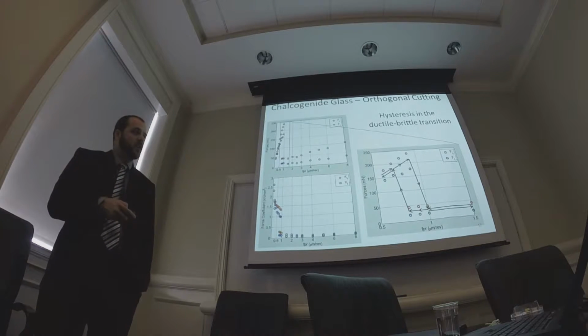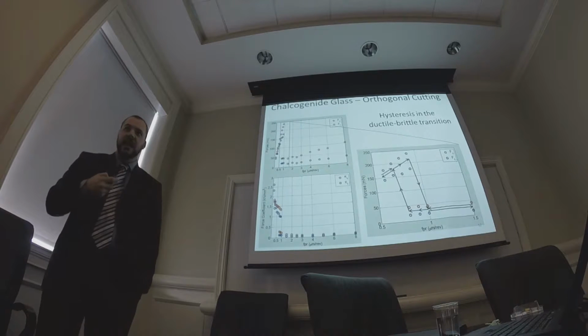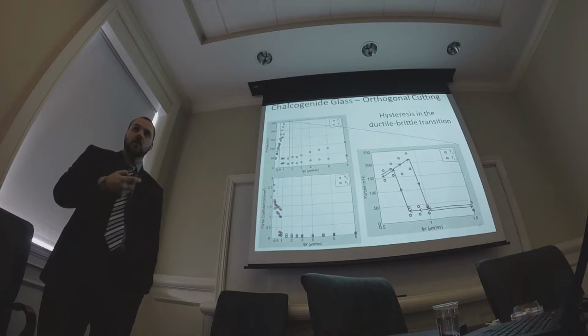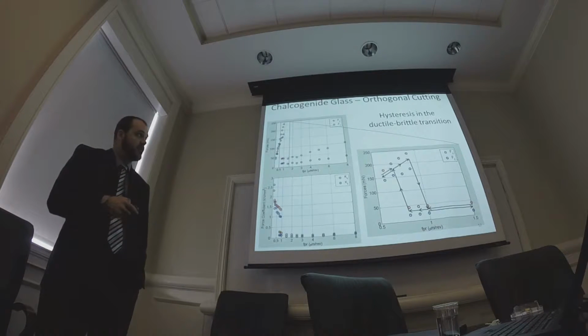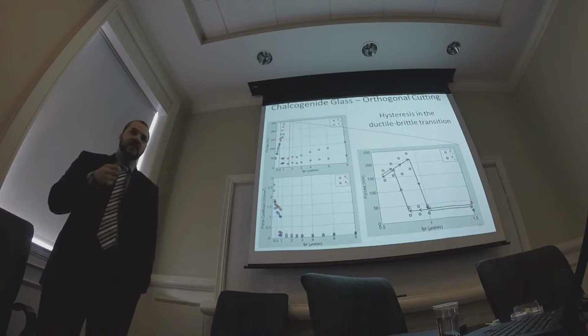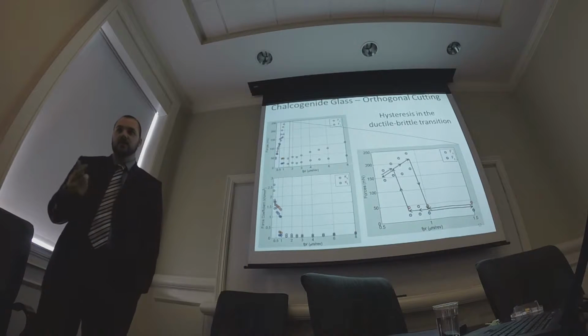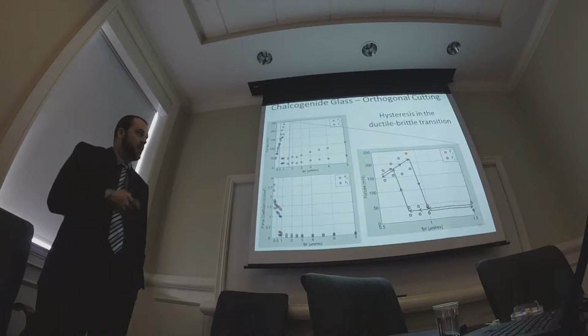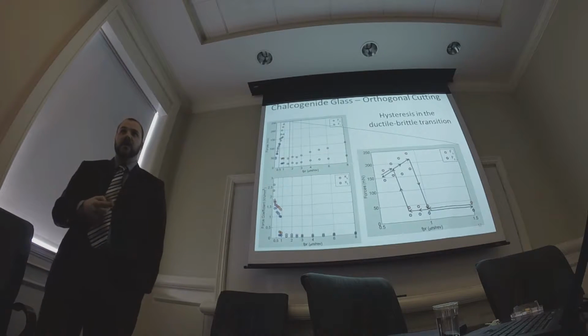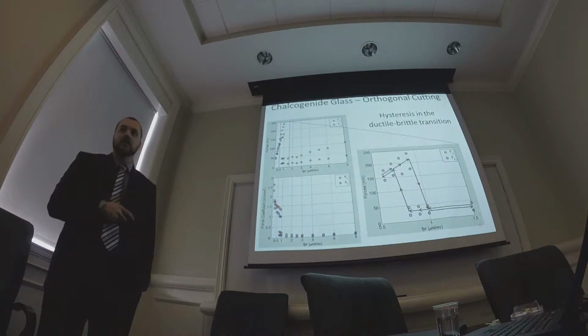If the surface is already fractured, it cannot get through the fracture without pushing the fracture even deeper, until it reaches some chip thickness that just does not want to fracture - it doesn't propagate fracture, is what I mean. So in these cutting conditions at 700 nanometers, it would not do anything but force is up here. Could not force it to be fractured.